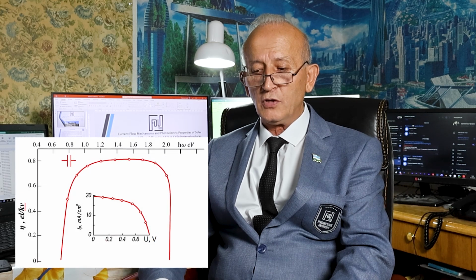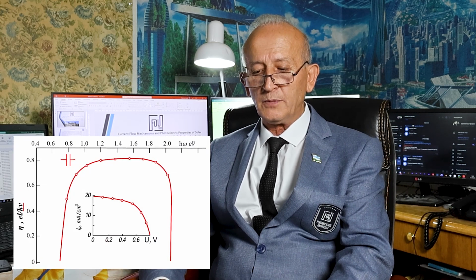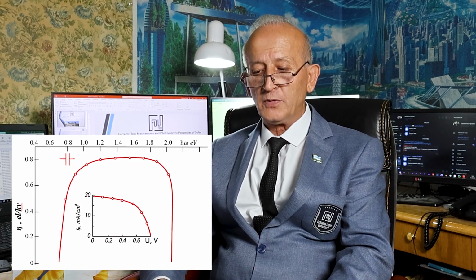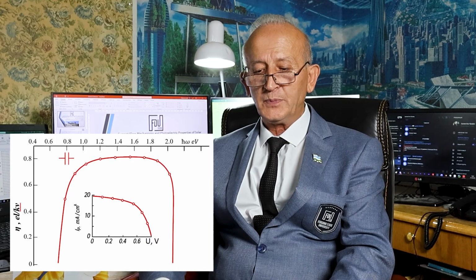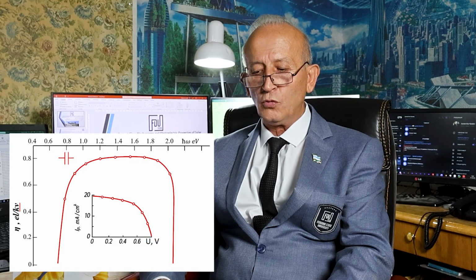As can be seen from figure 5, the photosensitivity spectra shift to the long-wavelength region of the spectrum, and this indicates that there are deep levels in the cadmium telluride responsible for impurity photoconductivity. By analyzing the absorption spectra, deep levels of activation energy were determined, as shown in figure 6.